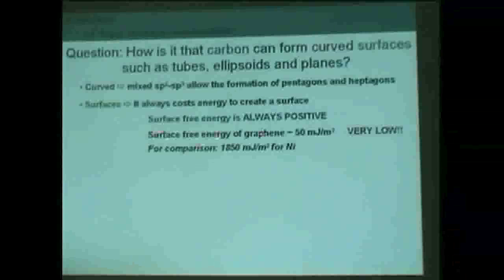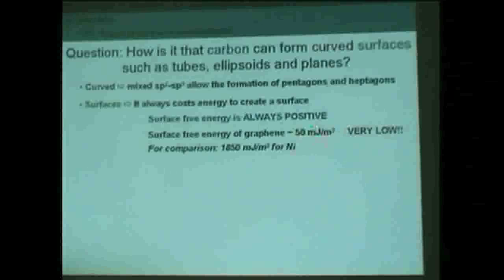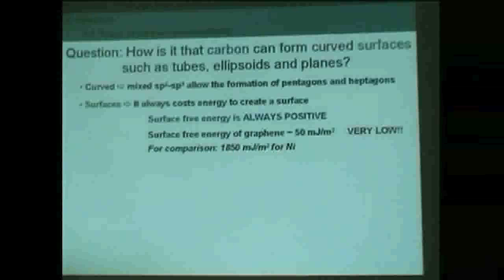What is special with graphene and a hexagonal network of carbon? What is special is this surface free energy is very, very low. It's 50 millijoules per square meter. And for comparison, for nickel, for a crystal of nickel, the surface free energy on a given side, I don't remember which one, but on average, let's say, is 1,850 millijoules.